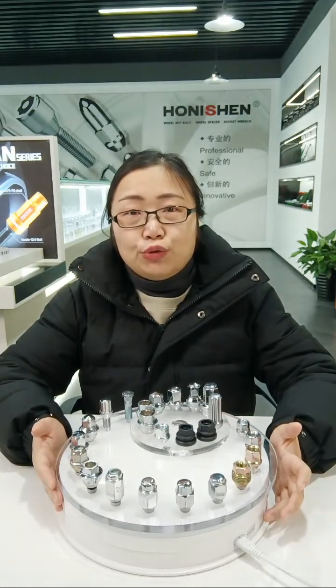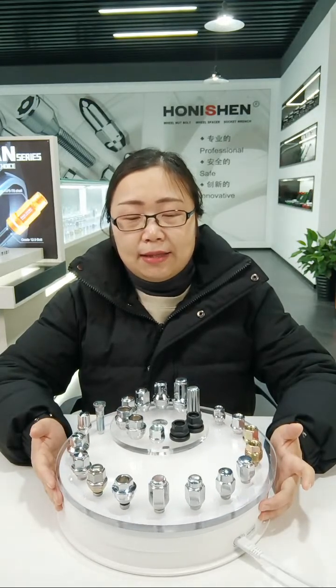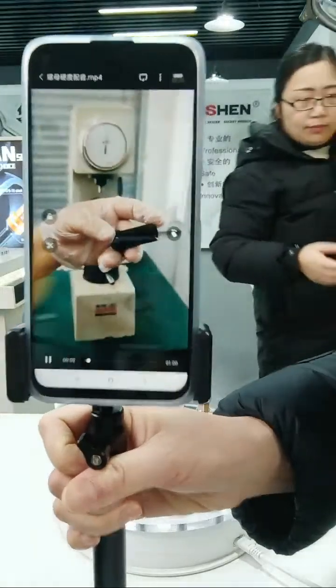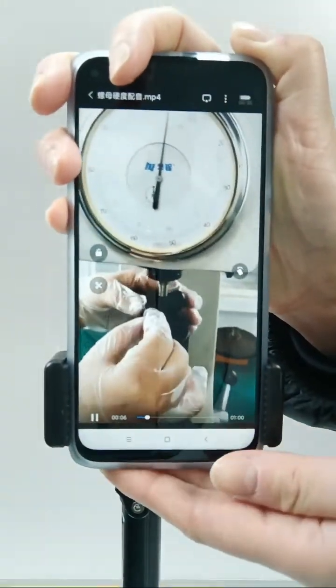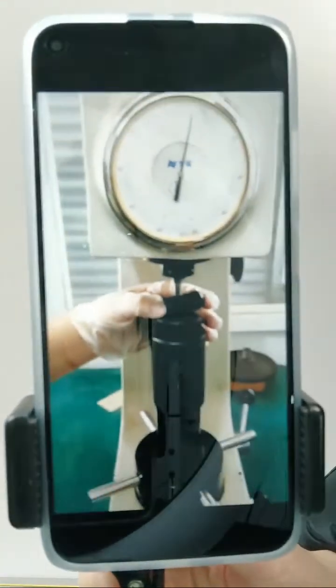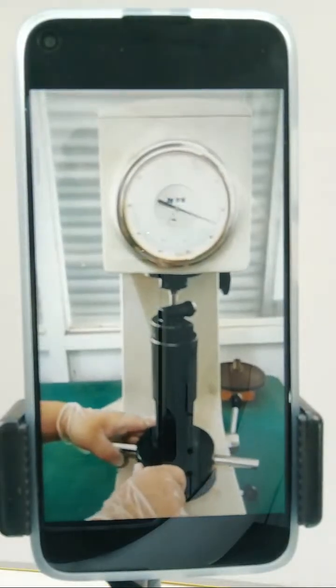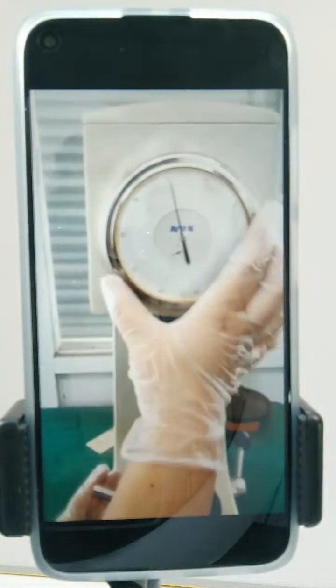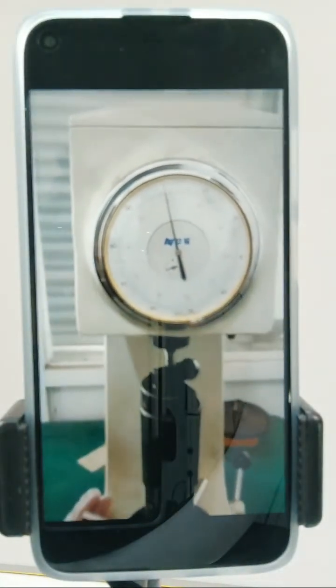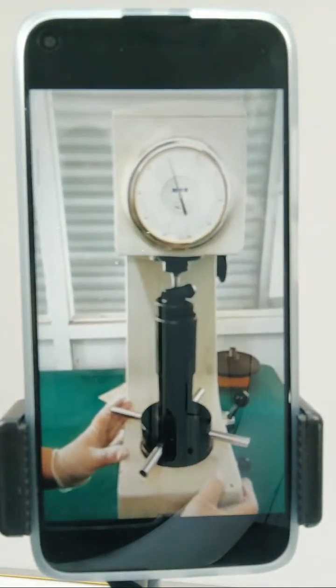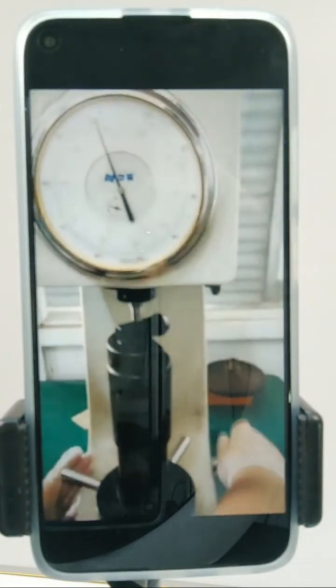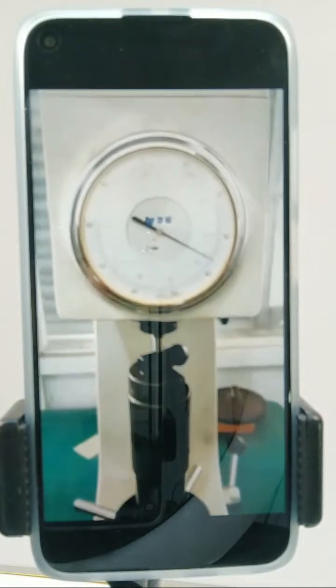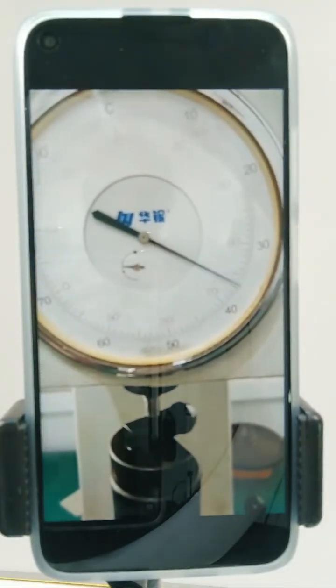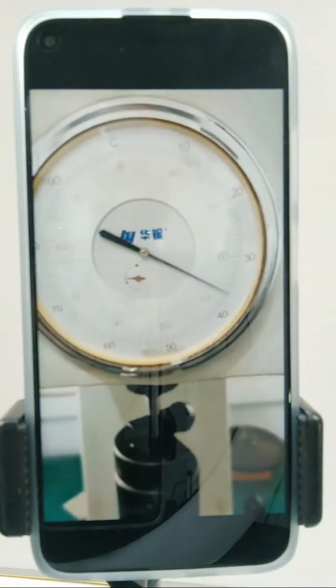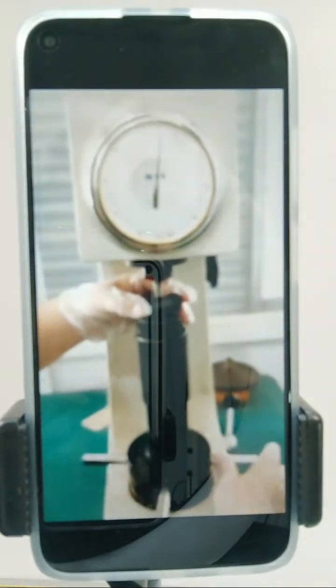Maybe some customers want to know how to test the lug nuts' hardness. Let me show you the hardness test for lug nuts. Take 8 grade lug nuts and put it on the table. Fix it. Then, spin the disc. Let the pointer aim at 0. C is equal to 0 in the machine. Push the handle. Push the handle again. After all this, we will get the last data. The test data HRC is 36.5. The international standard is HRC 23 to 32. Our test data is better than standard.